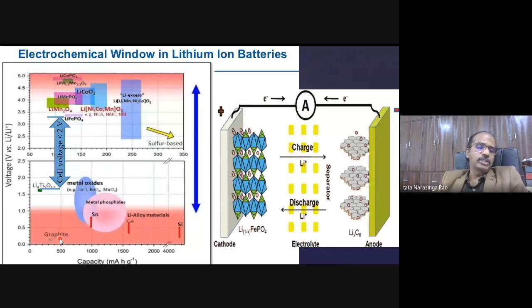And graphite is used on the negative electrode, the anode side. Here, graphite is in the red region. But you cannot use lithium foil, because that is dangerous: once you expose lithium to air, it burns like sodium. So instead of lithium we use graphite, and graphite as an anode is very close to lithium and gives very good voltage. But electrolyte decomposition also happens at this potential, and the graphite gets coated with an SEI, solid electrolyte interphase. Luckily, a lot of research has happened here, and people have optimized the kind of graphite and kind of electrolyte to give a nice SEI layer, which protects the graphite and allows the lithium to flow, but does not let the electrolyte decompose anymore. So graphite is used in all our batteries.